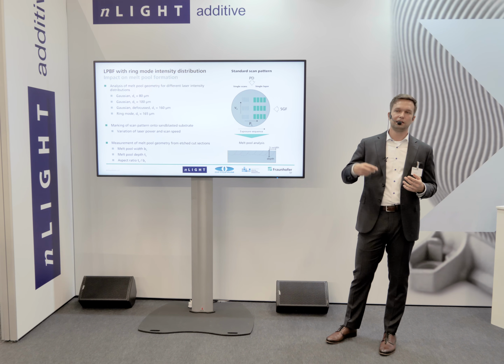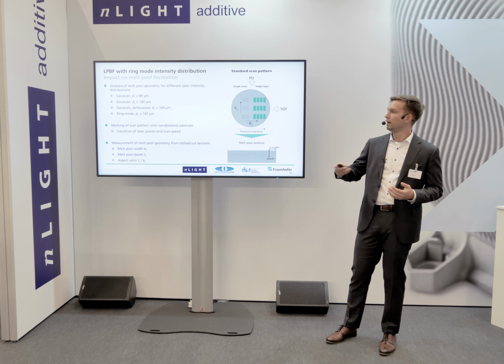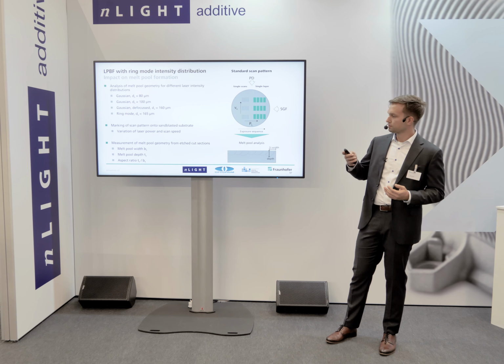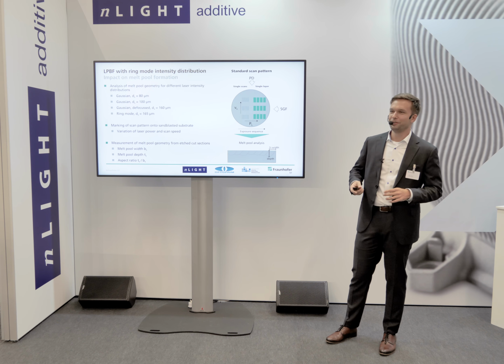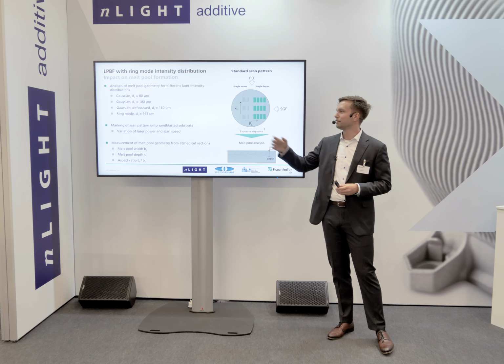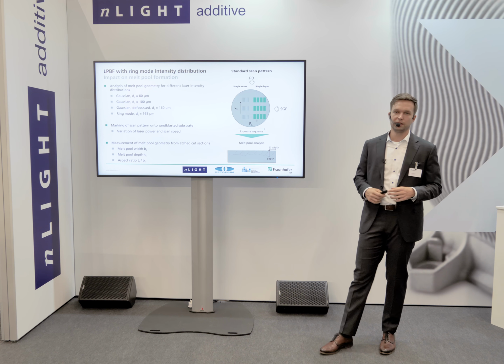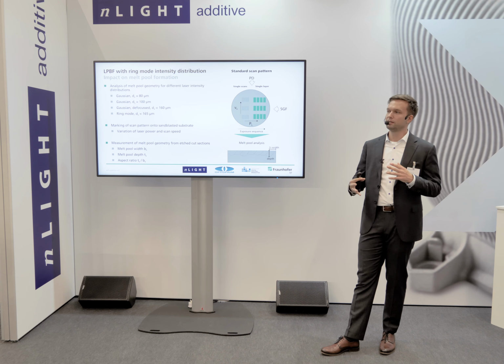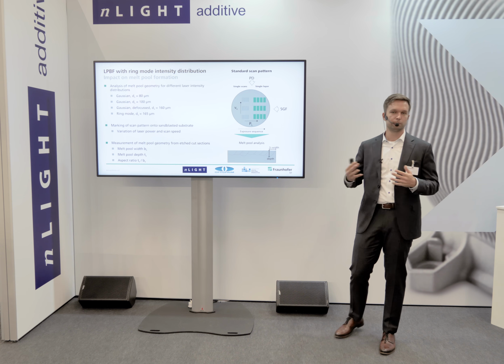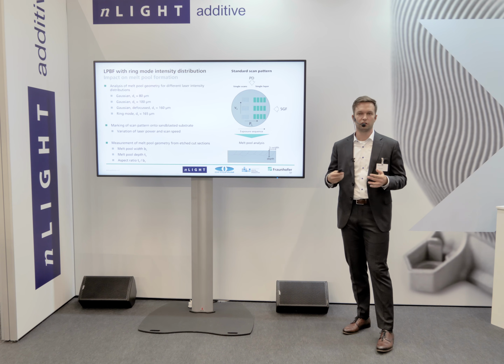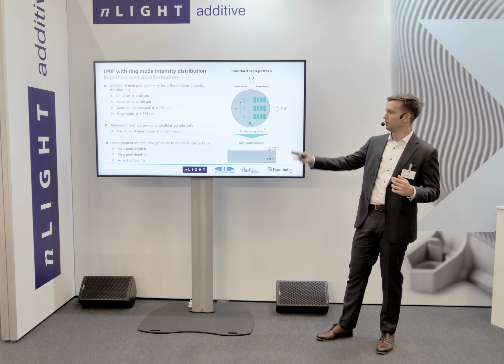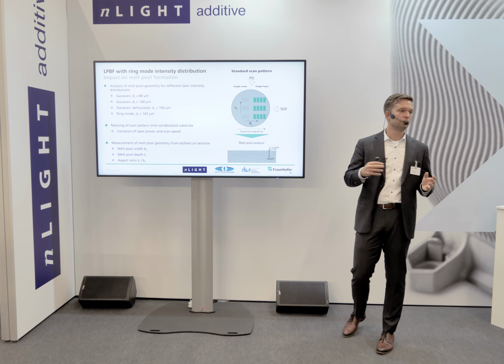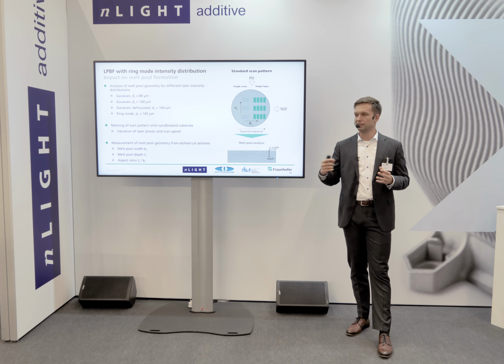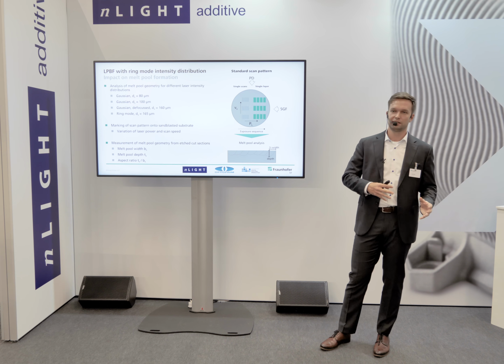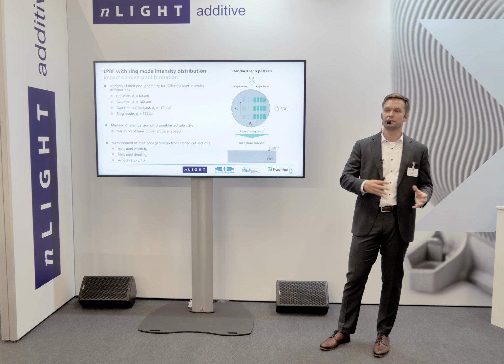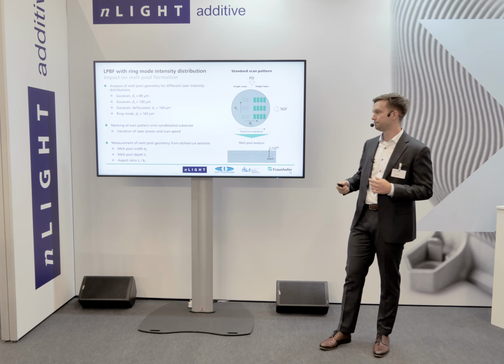We varied the laser power and the scanning speed, and we compared the 80 microns Gaussian and 100 microns Gaussian, which is considered state-of-the-art in most machines. Most machines work with 80 to 100 microns Gaussian intensity distribution. And we also took Gaussian defocused to 160 microns as a reference to see which impact the intensity profile itself has while having a similar beam diameter.